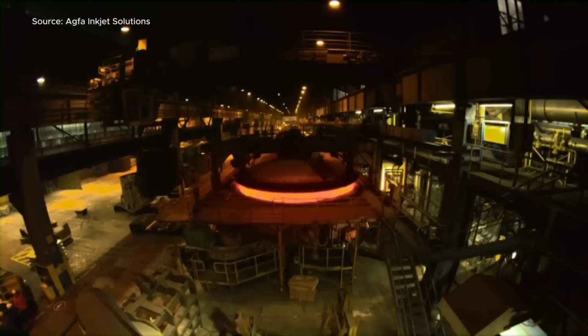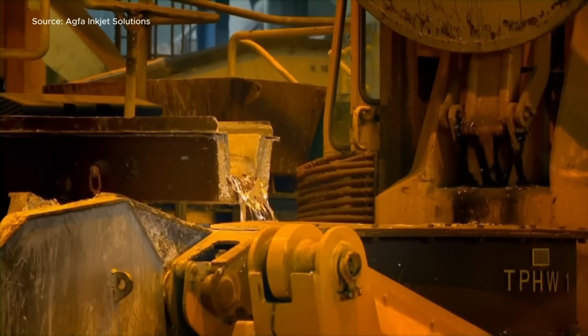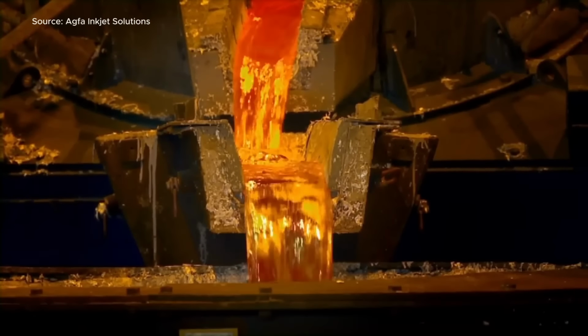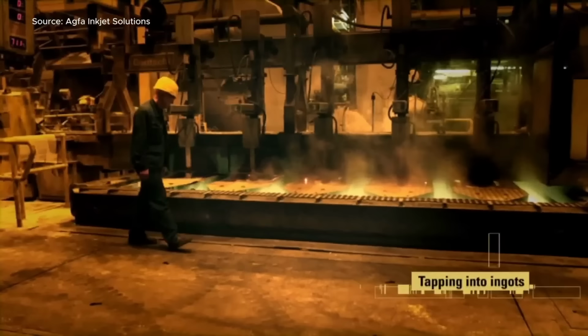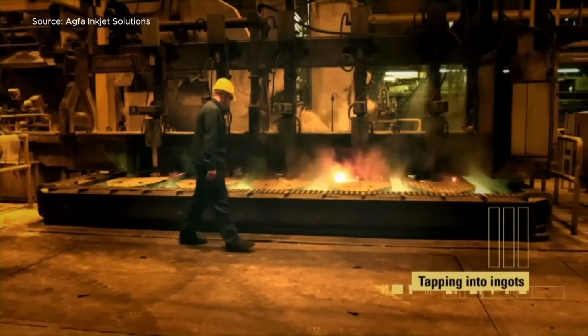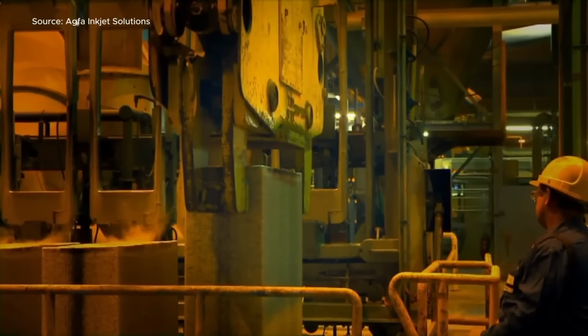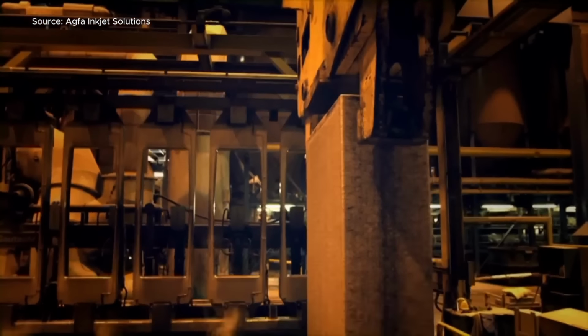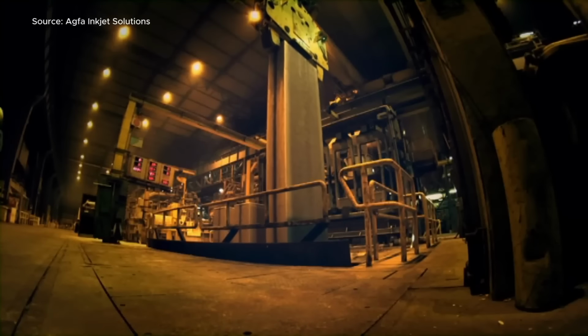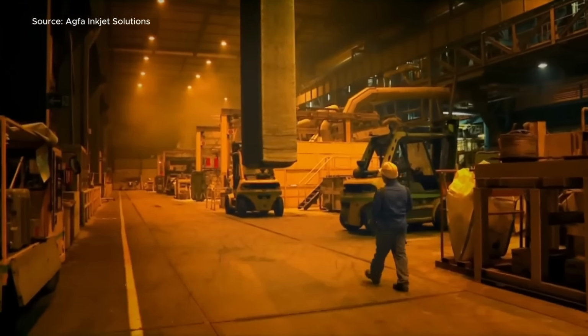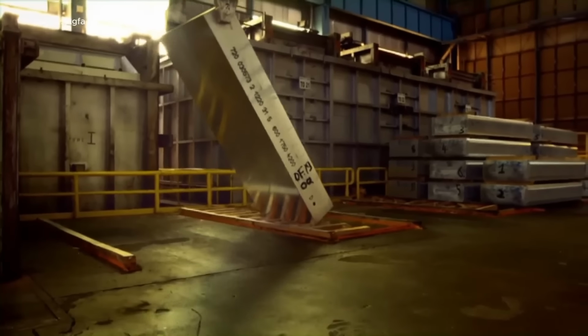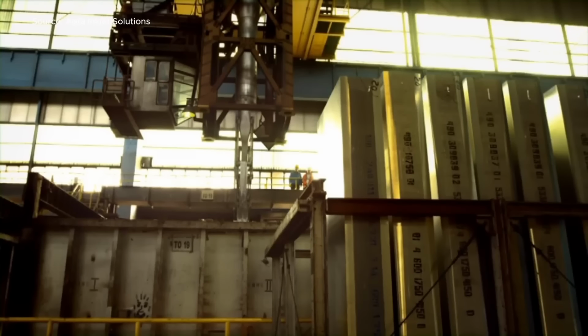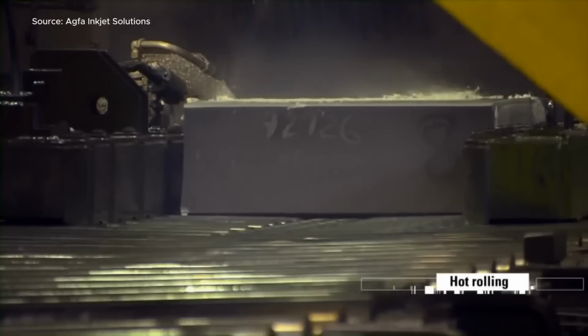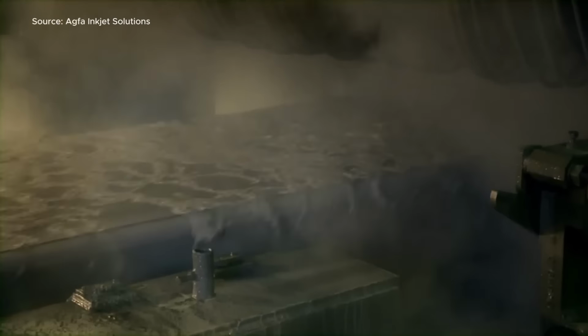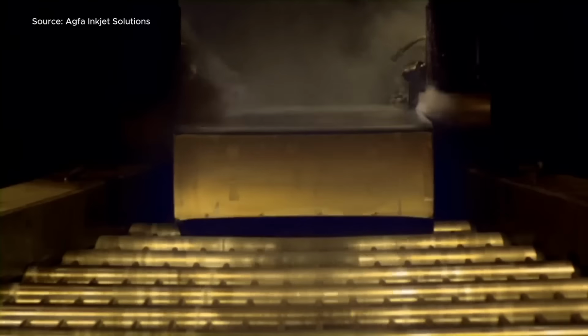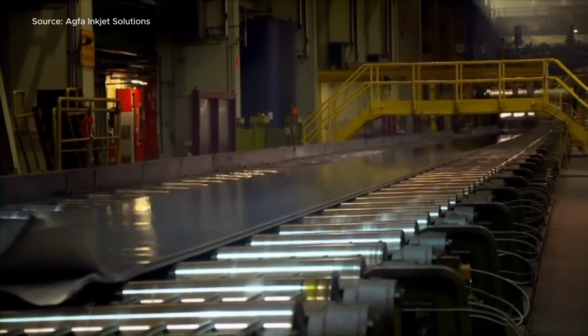From red earth to razor-sharp resolution, this is how a printing plate comes to life. It starts with bauxite, mined near the equator. From 2 tons of ore, just 1 ton of alumina is refined. Then comes smelting. At 700 degrees Celsius, pure aluminum is extracted via electrolysis and cast into 30-ton ingots. Hot rolling flattens these giants into coils 2.4 kilometers long and just 4 millimeters thick. Impressive, right? After cooling, they undergo cold rolling, thinning down to 0.15 to 0.3 millimeters depending on the application.